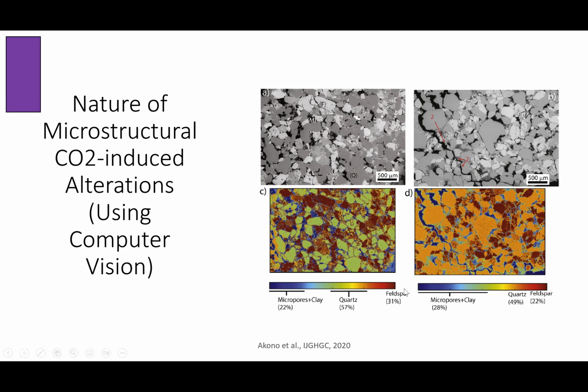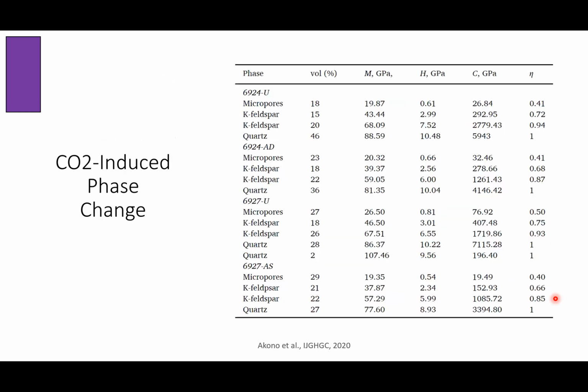So we have on the left an unaltered sample, and then on the right, we have something that's altered. And we can see we have the same trend: as the result of incubation in CO2 saturated brine, we have an increase in the fraction of porosity, we have a reduction in quartz pointing to a dissolution of quartz, but we have the highest reduction in feldspar, we are dissolving feldspar. So it's really good to have, on the one hand, nano-indentation, statistical deconvolution, and then on the other hand, scanning electron microscopy imaging along with computer vision, and they agree, yes, we are dissolving feldspar, we are increasing the fraction of micropores in this case.